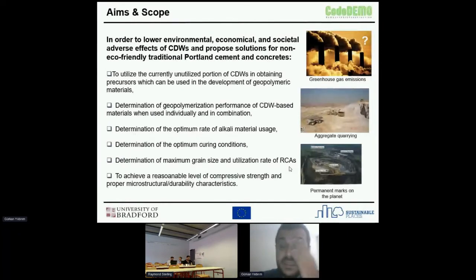And another issue is we need to use aggregates inside a certain binder to obtain mortar or concrete. What will be the maximum aggregate size, and the volume or utilization rate of recycled concrete aggregates? And in the end, we need to achieve reasonable compressive strength and a material with microstructural and durability characteristics similar to or better than traditional concrete. By doing this, we get rid of aggregate quarrying, we get rid of the permanent marks on the planet caused by the production of Portland cement, and we also reduce greenhouse gas emissions significantly.